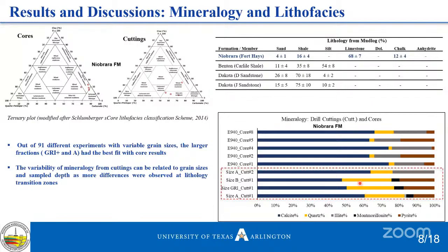Those ones seem to have more siliceous content and less carbonate content. But when the size is increased, like this size A, you find out that it matches more to that of core. So this is very important, and it allows you to make your choice in terms of what size I am going to use if I want to do my analysis with cuttings. From this research, we found out that the bigger the size, the closer you are to what you can get from core information.